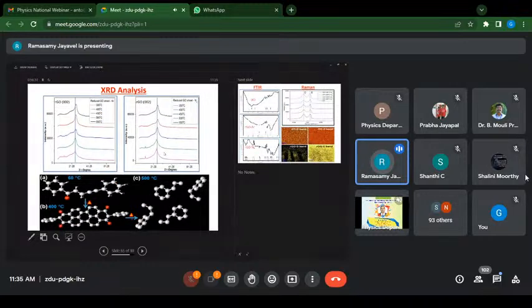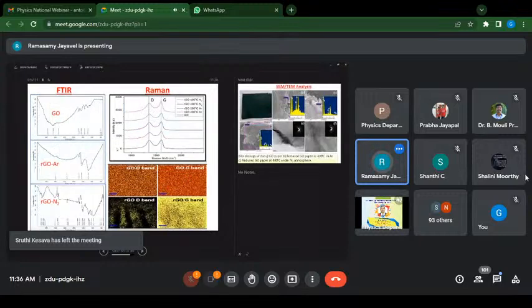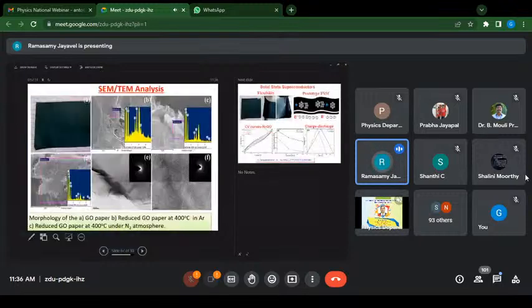And we also did some molecular simulation studies to fix the annealing temperature without any impurities. And see, this is at room temperature at 60 degree, where at 400 degree the molecule is very intact. At 500 degree it disintegrates. So the maximum annealing temperature would be around 400 or 450. With the 500 it collapses. So we did for both argon as well as nitrogen atmosphere, and lower annealing temperature leads to this kind of impurity peaks.